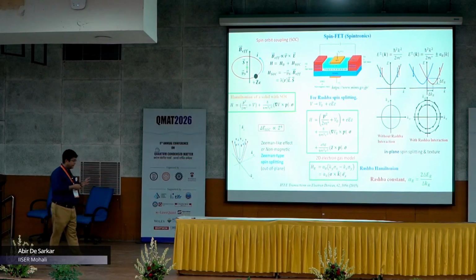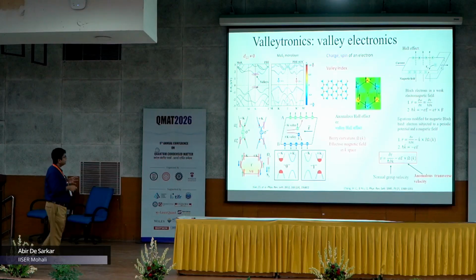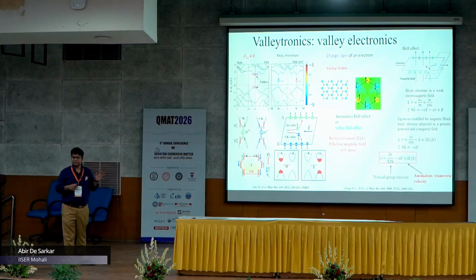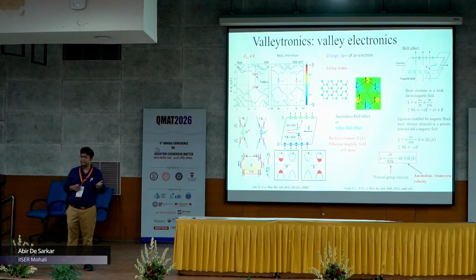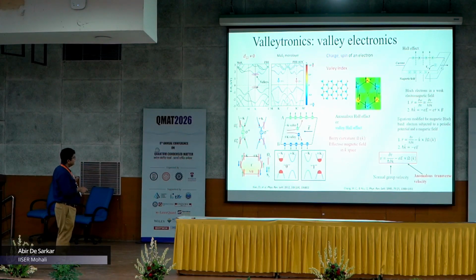Okay? And then apart from the charge and the spin degrees of freedom of an electron, another degree of freedom, namely the Valley degree of freedom, arises in single layer MoS2. So, this is the top view of single layer MoS2, which shows that the inversion symmetry is broken in the XY plane of this monolayer, for which it shows an in-plane piezoelectricity, and this is the band structure which has been calculated in the absence of spin-orbit coupling.